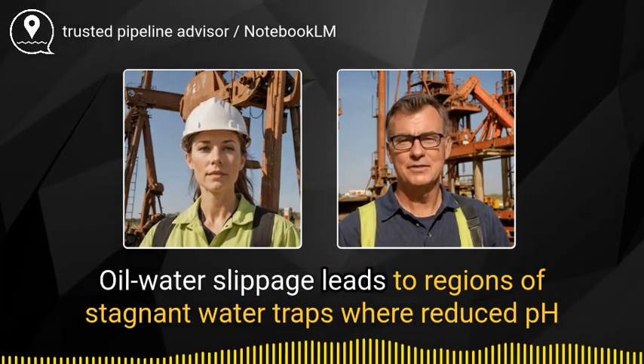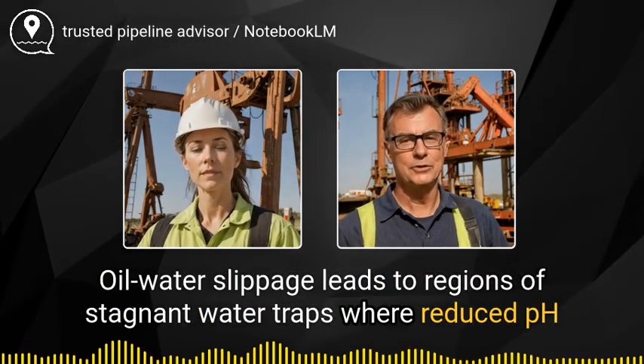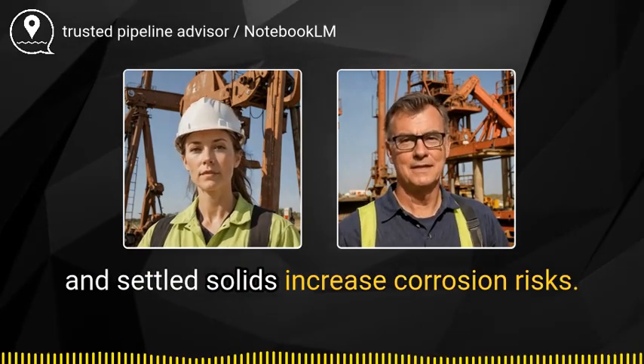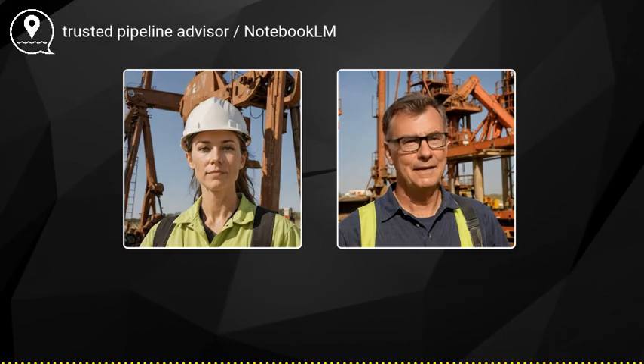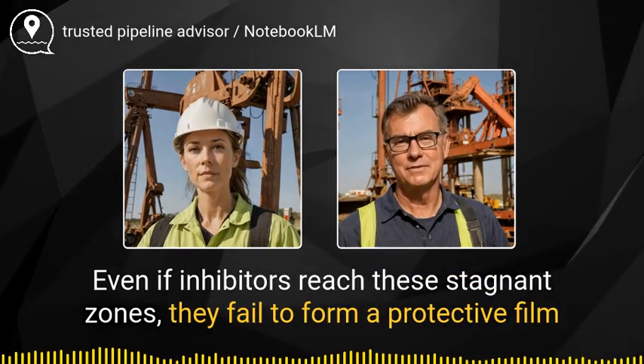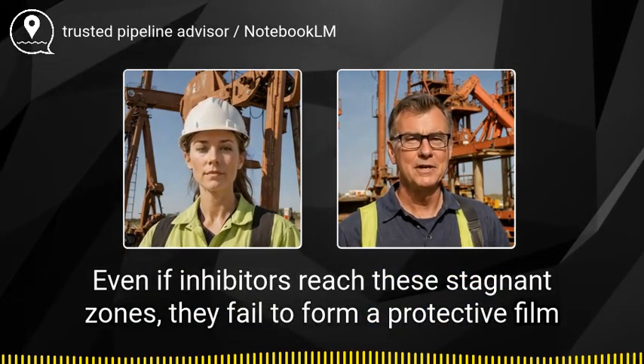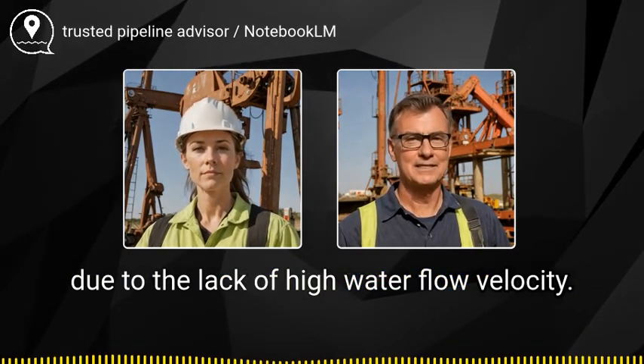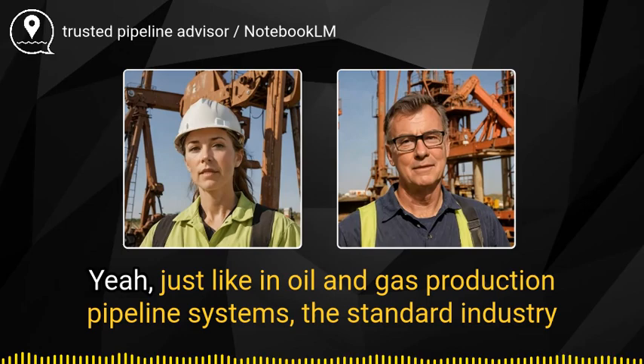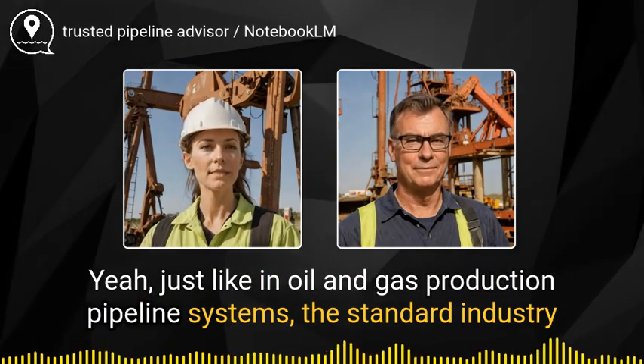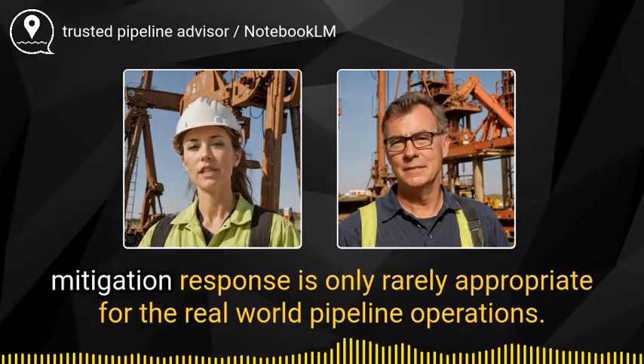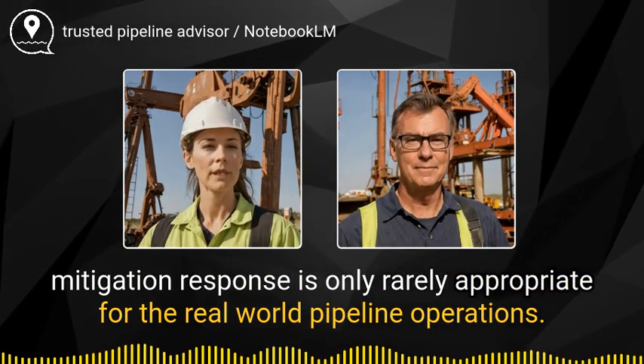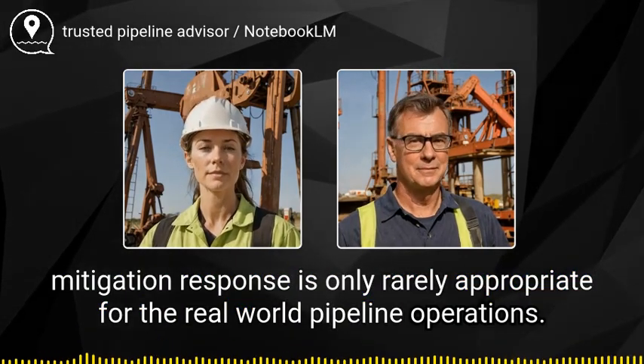Oil-water slippage leads to regions of stagnant water traps where reduced pH and settled solids increase corrosion risks. Even if inhibitors reach these stagnant zones, they fail to form a protective film due to the lack of high water flow velocity. Yeah, just like in oil and gas production pipeline systems, the standard industry mitigation response is only rarely appropriate for real-world pipeline operations.